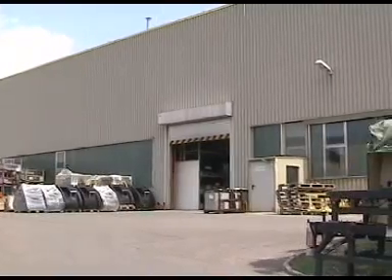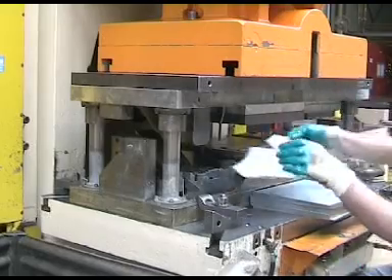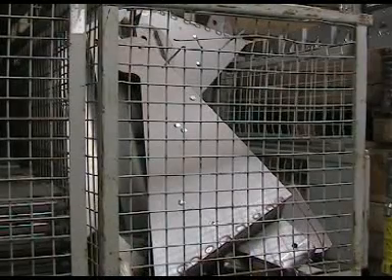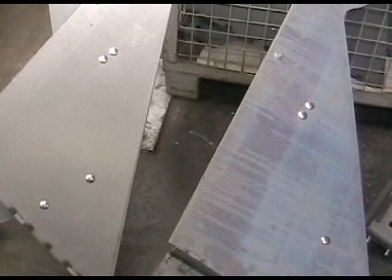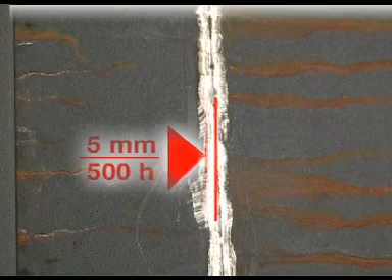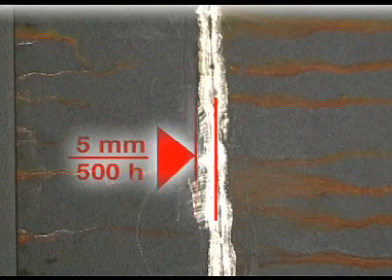Iron components have to be degreased before they can be painted. Thin film phosphating is often performed to improve the adhesion of paint or powder coatings. Paint adheres better to a phosphated surface than to an untreated surface. Second advantage, corrosion hardly spreads from a damaged point. On a test sheet, it advanced no more than 5 mm within 500 hours in a salt mist.